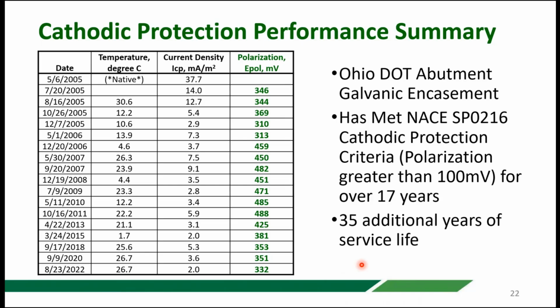And the other thing that they can monitor by monitoring the current flow over time is how much additional life, how many more years you have out of the anodes. And based on their monitoring, they're going to get an additional 35 years of service life based on the anodes they put into the abutment here. So that's one example, and I just use that.